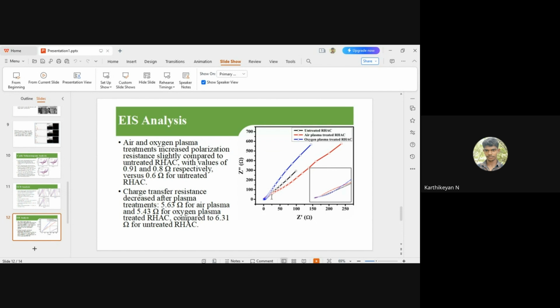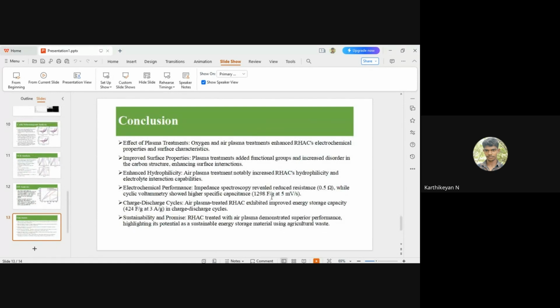The final conclusion, the effect of plasma treatment: the oxygen and air plasma treatment enhanced RHAC electrochemical properties and surface characteristics. The plasma treatment added functional groups and increased disorder in the carbon structure, enhancing surface interaction and hydrophilic nature. The air plasma treatment notably increased RHAC hydrophilic nature and electrolyte interaction capability.